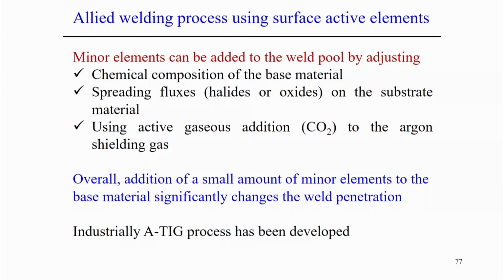First is that minor elements, that means either oxygen or sulfur, in general we consider these two components, can be added by adjusting the chemical composition of the base metal. This is one way. That means the surface active elements already become part of the base metal, and when you weld that base metal, there will be the effect of the surface active elements. Or the other way is simply spreading the fluxes, that means halides or oxides, on the substrate material. So, simply coating the oxides on the material which is supposed to be welded. In that way also it is possible to supply the surface active elements.